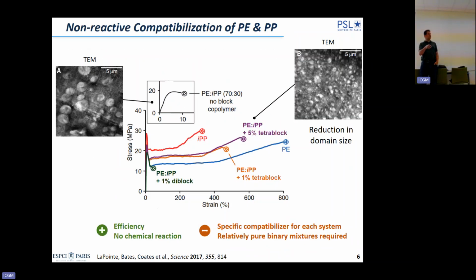And here you have TEM. So this is TEM of the blend of PE and iPP, 70-30, the same I showed you. So a strong phase separation, a very fragile material. And by adding block copolymers, I'm not going to cover all of them, they were able to go back to a material with very good mechanical properties, which is ductile. So this is very efficient, no need for chemical reaction. If we had to point toward something that could be improved, it's not so easy to make these block copolymers, and they are specific to the blend you want to recycle.